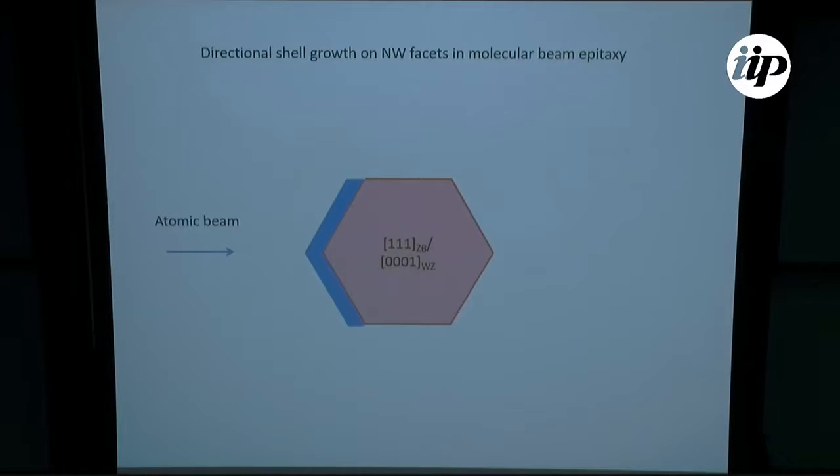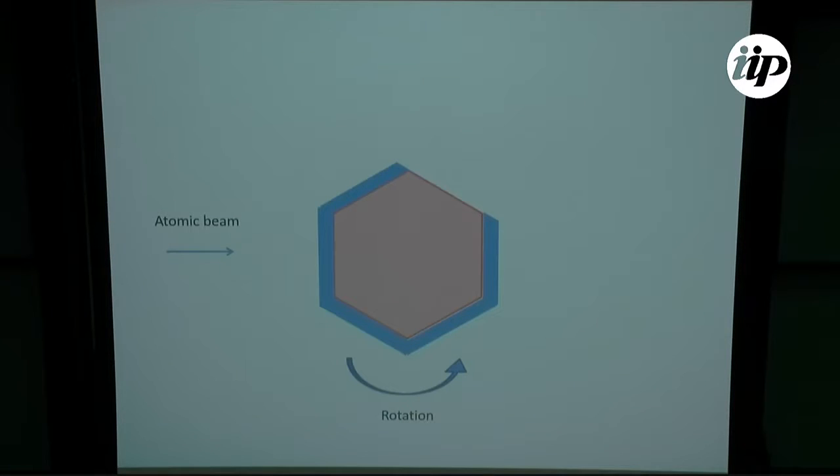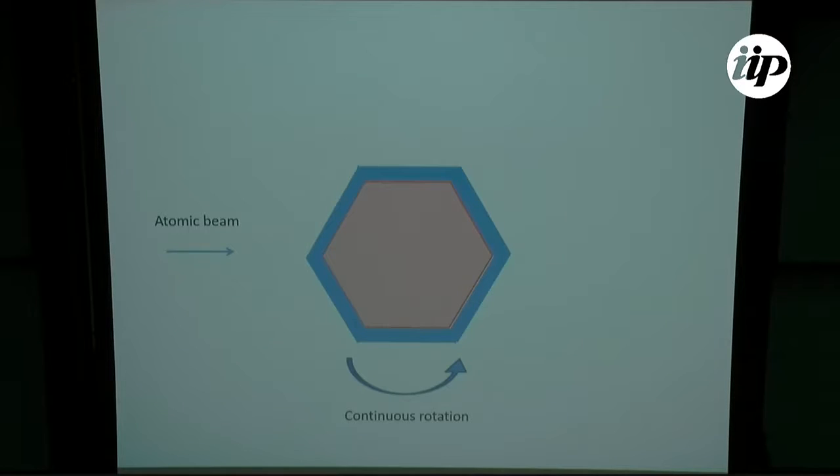So, for example, if you know the crystal orientation of your wafer, and you know the orientation of your beam of atoms coming in, and you also know the faceting of your crystals, then you can put, for example, your superconductor on 2 facets here, and all 3 facets, and so on. Or we can even choose to put it on 2 facets here, 2 facets here, and a different material on these 2 facets. So there are much more interesting degrees of freedom in making nanowires, but it's not, of course, as scalable. So I think Microsoft would like me to go to 2DEG and select area growth at least, so they can build a quantum computer.